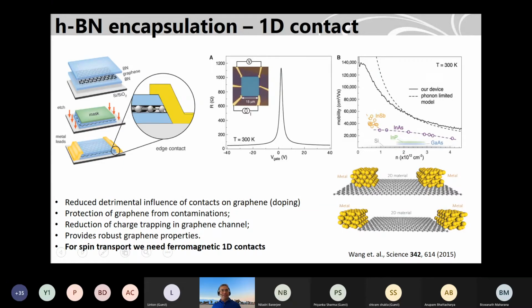And the edge contacts can be very useful because the carbon has a dangling bond here, and the contact can transfer electrons very well in the system. And this was first demonstrated in 2015, and this gives rise to very high mobility graphene. So this is a Hall bar, this is a van der Pauw method. So this is a graphene boron nitride heterostructure device here. And you see this is the Dirac curve. It's very sharp, very close to zero, so very low doping.